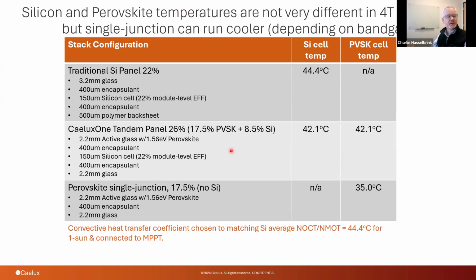And as you find, with these assumptions in here, you would find that the traditional silicon panel, as we would guess, is 44.4 degrees Celsius. We have tuned the convective heat transfer coefficients so that they exactly match what we saw in those data sheets.